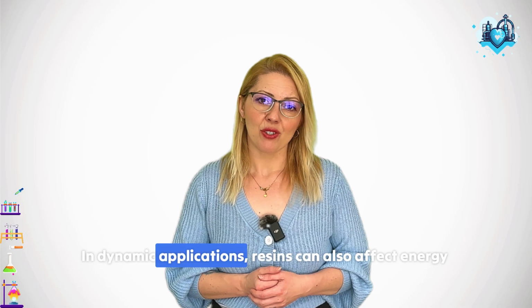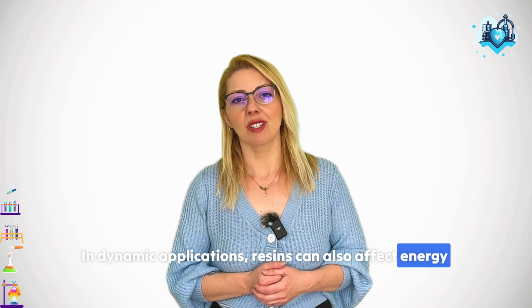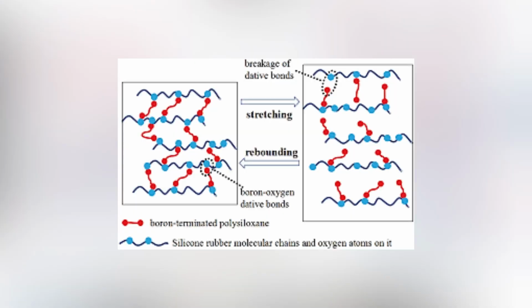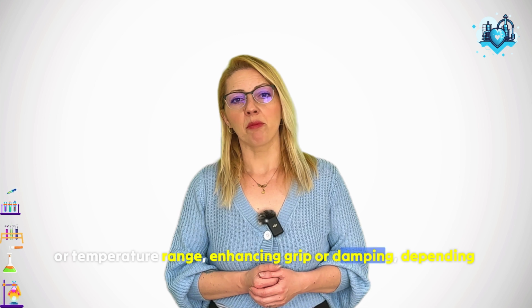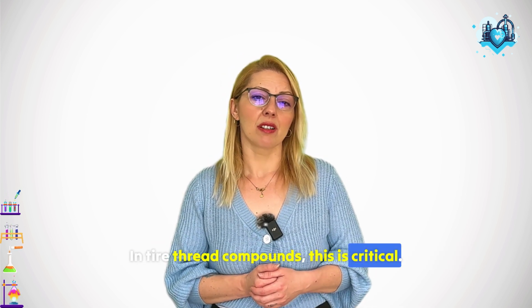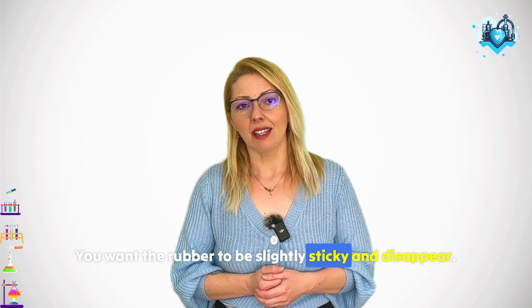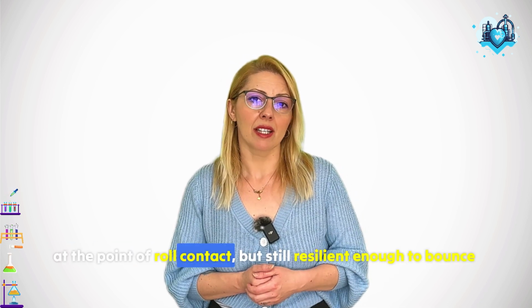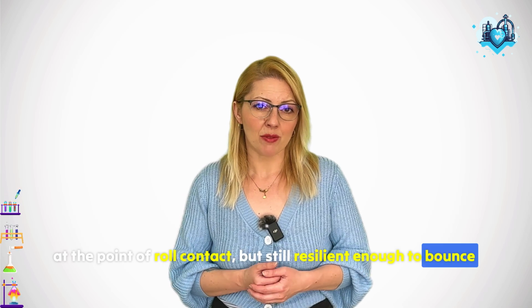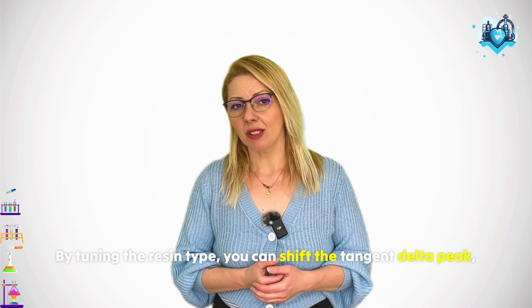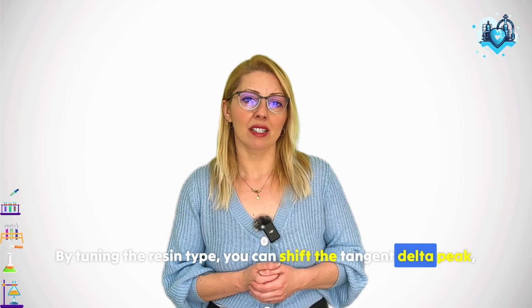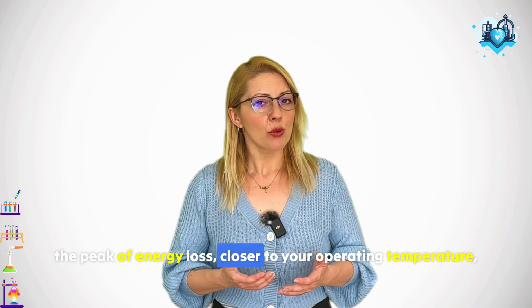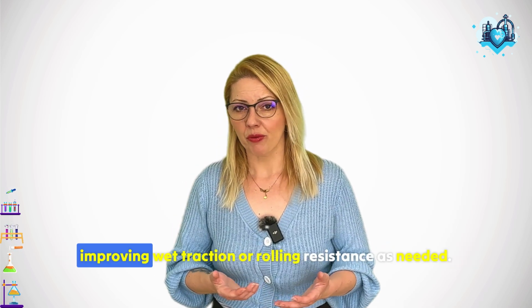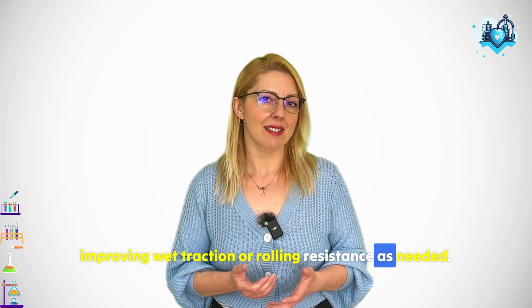In dynamic applications, resins can also affect energy dissipation. They can increase the loss modulus in a specific frequency or temperature range, enhancing grip or damping, depending on the use case. In tire tread compounds, this is critical. You want the rubber to be slightly sticky and dissipative at the point of road contact, but still resilient enough to bounce back after deformation. By tuning the resin type, you can shift the tan delta peak, the peak of energy loss, closer to your operating temperature, improving wet traction or rolling resistance as needed.